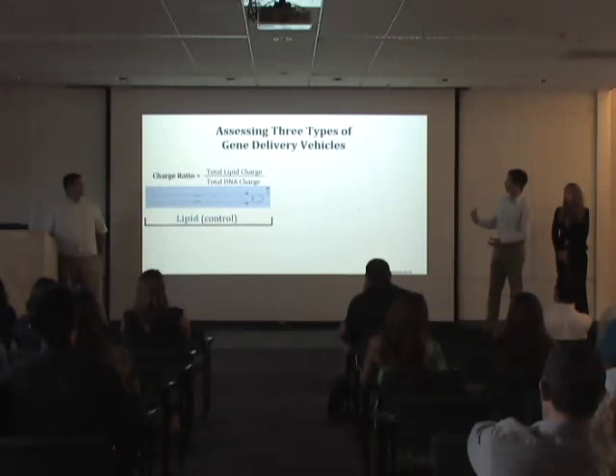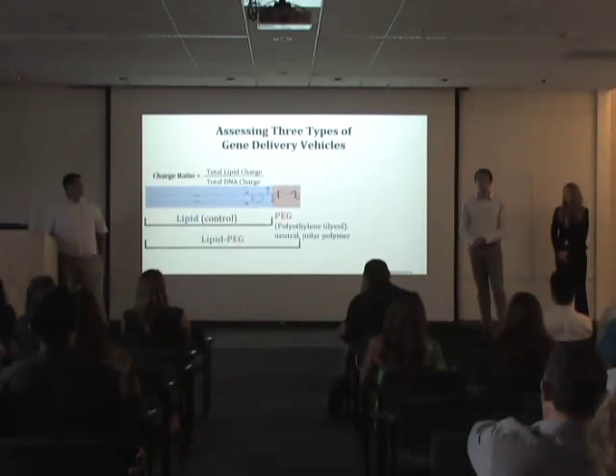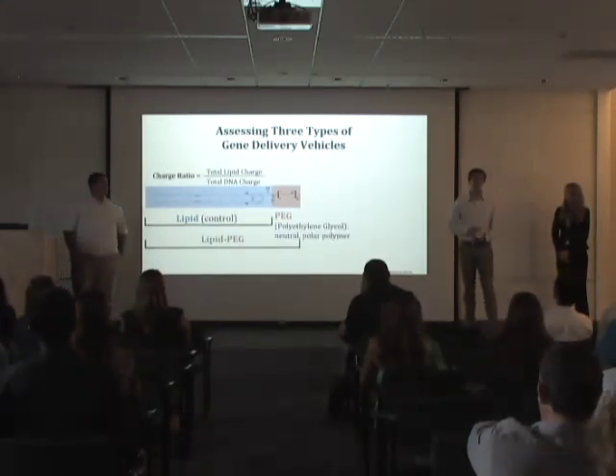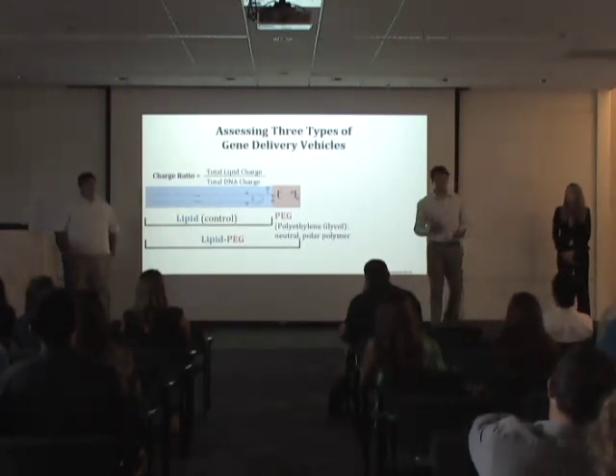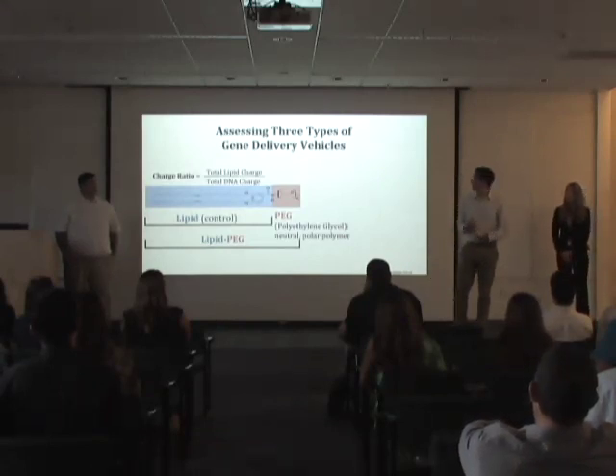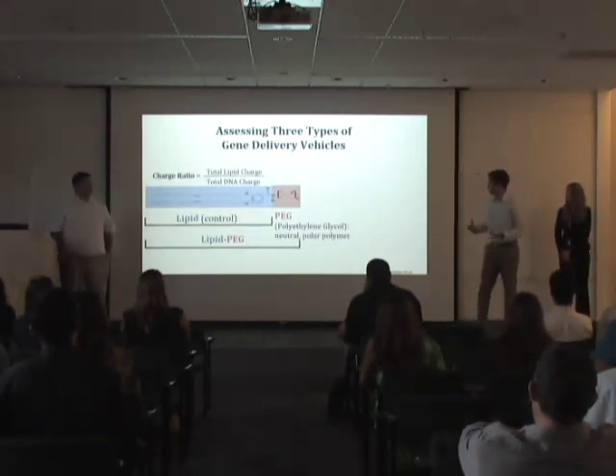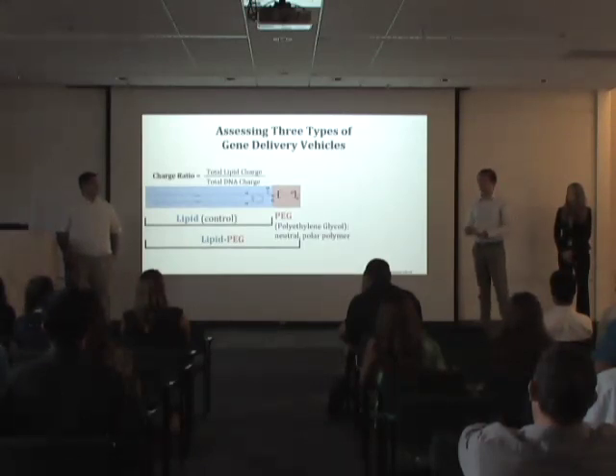To increase the lifetime of lipid nanoparticles in medicinal applications for humans, we have coated it with polyethylene glycol, or PEG. PEG is important because not only does it increase the duration of the lipid nanoparticle in the bloodstream, but unfortunately it also makes it more lubricated and less likely to adhere to cells.